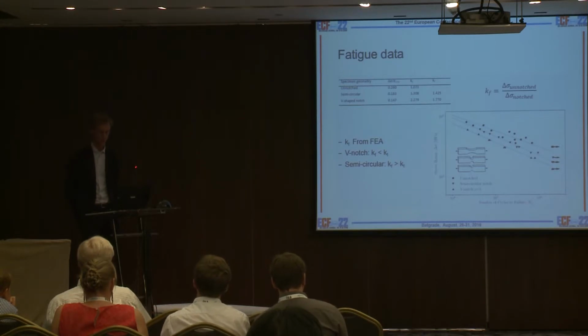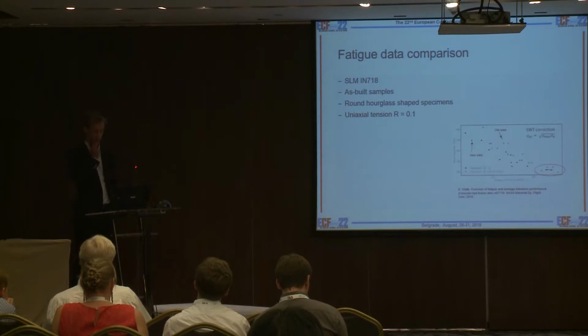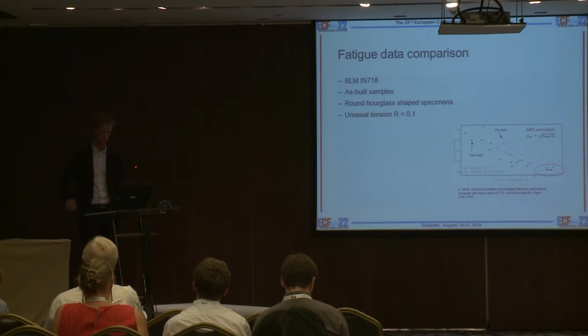So for the V-shaped notch, the values are within what's expected, but for the semicircular, we have a higher fatigue notch reduction. So we had to look into this. First I'll compare the unnotched specimen. These are some other results reported for also uniaxial fatigue, hourglass-shaped specimens. And we can see that I've corrected it with the mean stress correction. And in the fatigue limit, there is a good correlation. There is also a slight difference in the slope, but it's in the same range.